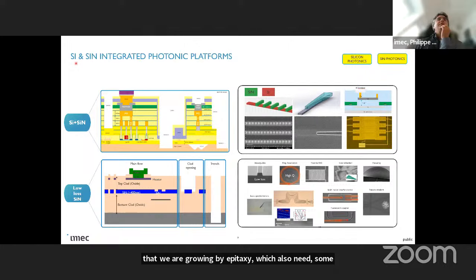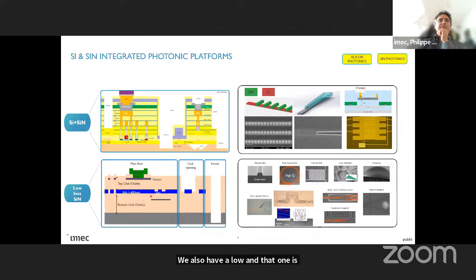This is the first platform where you can see we are stacking the SOI, we are putting the silicon nitride, and then we have back-end of line type of processes that we are running. We also have a low-loss silicon nitride, and that one is the high-temperature nitride, which goes into dB per meter range usually. So for some application, specifically in quantum, they are really chasing the photons. And we do use this platform for this kind of application where the losses are extremely important.